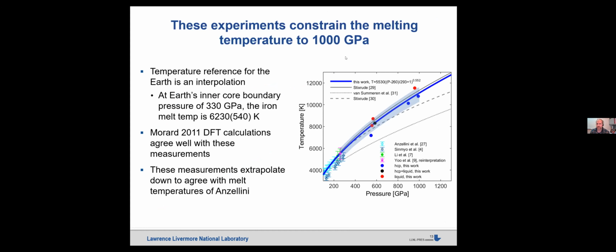So using this technique, this two-step thermodynamic integration, we can obtain the melt curve from the reference point at 260 GPa along the Hugoniot up to 1000 GPa where our data tops off. And then we performed a Simon fit to the data and extrapolated that both up to higher pressures and to lower pressures. So I'd say the one nice thing this provides is the temperature reference for the Earth: the melting curve of pure iron at 330 GPa at the inner core boundary is now in an interpolative regime rather than extrapolating up from the static high pressure measurements at lower pressure. And so we found that the temperature at 330 GPa for pure iron is 6230 plus or minus 540 degrees.